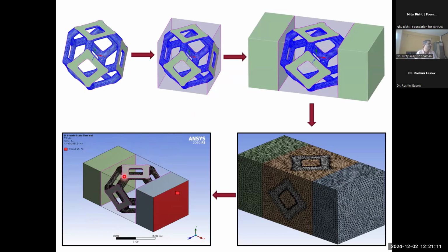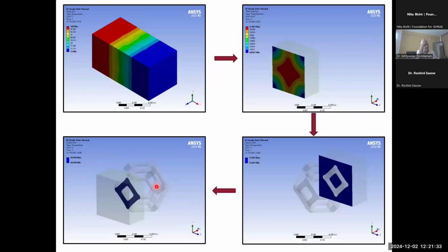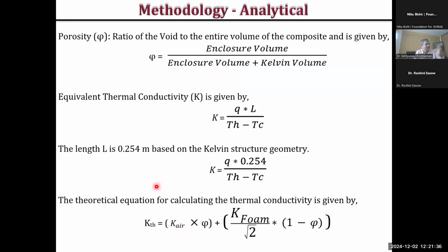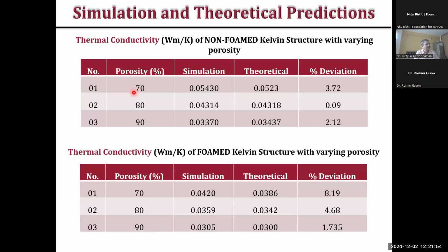This is how the Kelvin structure looks like. Small, all are these struts. These are forming a hollow space again. And why hollow space? Already I mentioned it. Being in the syntactic foam area, I know how we can make this hollow space beneficial for different applications. We did the simulation and got all these results way back in 2021, I guess. Then from all these simulations, we wanted to know the enclosure volume. What is specifically the Kelvin volume? And then using empirical equations which are available, we found out the effective thermal conductivity. Then we compared the effective thermal conductivity through simulation and theoretical means. These are non-foamed ones, and this is a foamed one.